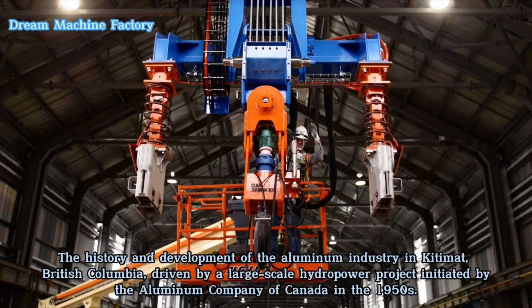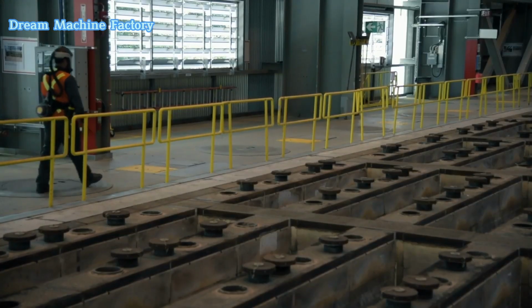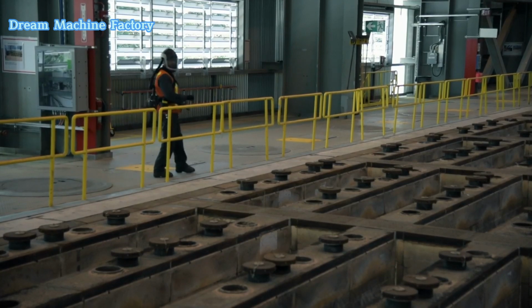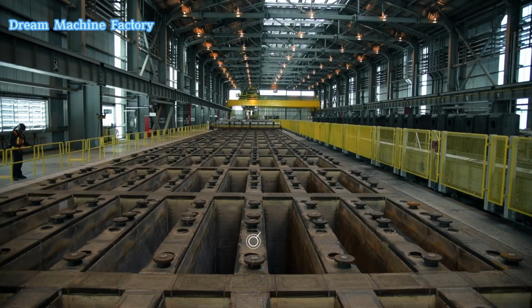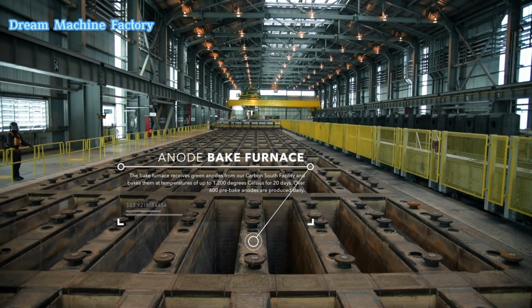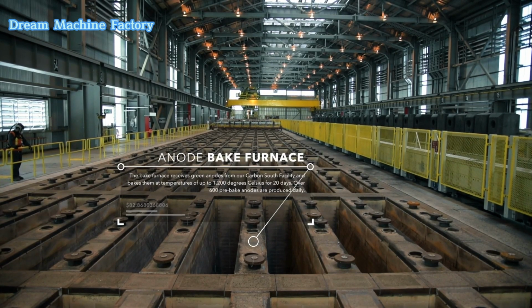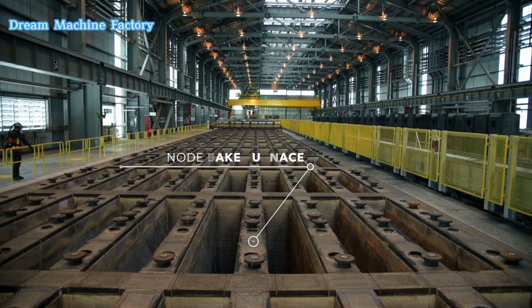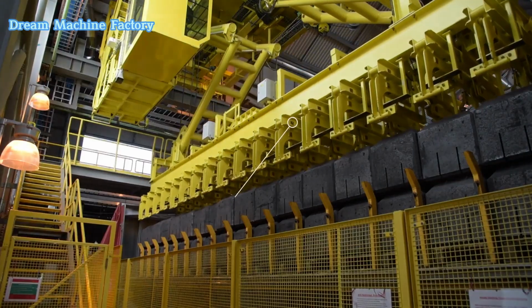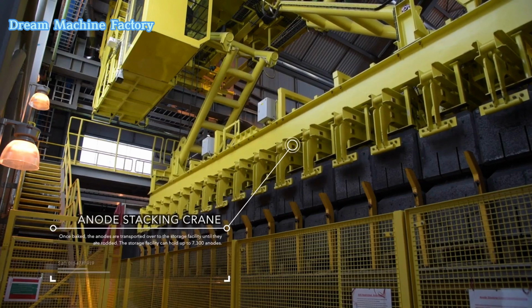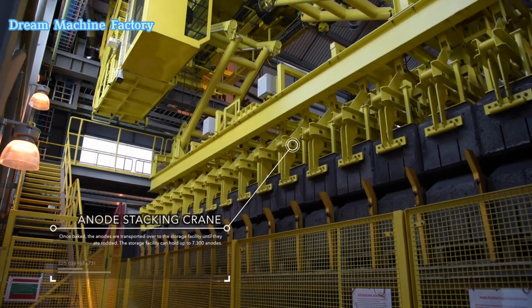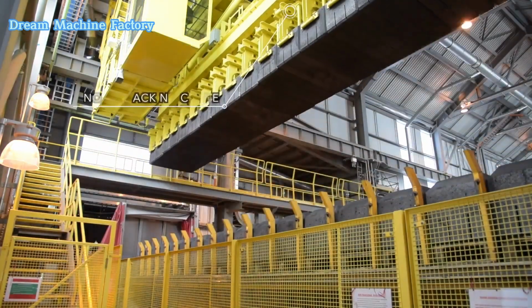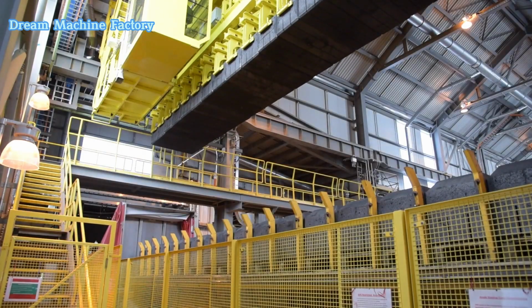The anode bake furnace is a critical component of the smelting process, receiving green anodes from the Carbon South facility and baking them at temperatures reaching 1,200 degrees Celsius over a 20-day cycle. It produces over 600 high-quality pre-baked anodes daily. The anode stacking crane transports baked anodes to the storage facility, efficiently organizing up to 7,300 units for later use.